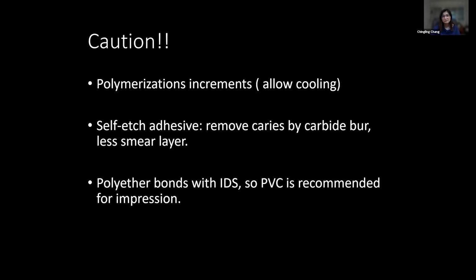And if we remove the caries by the carbide bur or the hand instrument, we generate less smear layer, so we can use self-etch adhesive. But if you remove the caries by using a high-speed diamond instrument, the total etch technique is recommended. Also, when we take an impression on the tooth with the immediate dentin sealing procedure, we should use PVS impression material because a polyether material actually bonds to the bonding agent on the dentin surface.